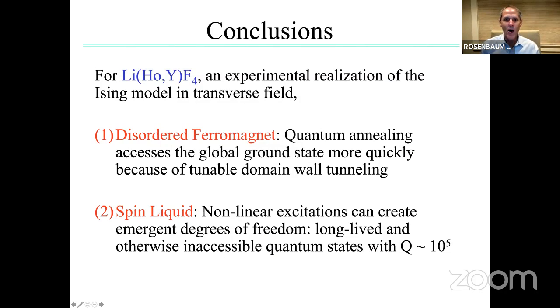This is lithium holmium yttrium tetrafluoride. It's an experimental realization of the Ising model in transverse field. You can look in different regimes. I've told you about 2 of them. One is the disordered ferromagnet, and here the quantum annealing gets you to the global ground state much faster. And we can microscopically model this and tell you about the domain wall tunneling in a quantitative fashion.